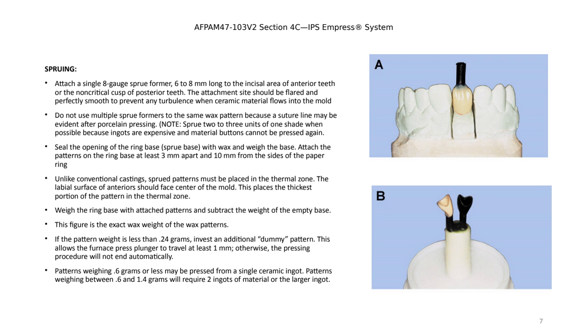The gauge of the sprue also differs depending on the type of restoration — whether we're doing a coping or a full contour. This must be taken into account before spruing. Typically, a single 8-gauge sprue former, 6 to 8 mm long, is attached to the incisal area of anterior teeth or the non-critical cusp of posterior teeth.